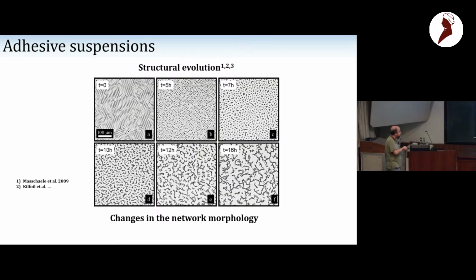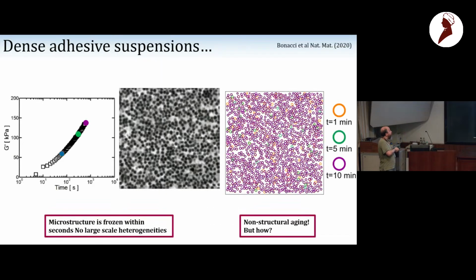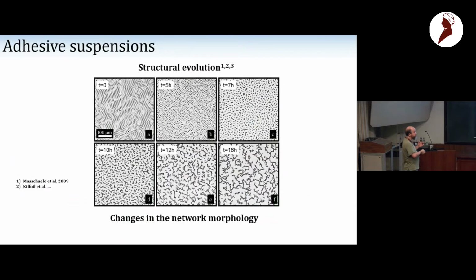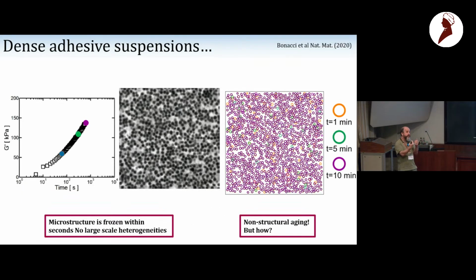Even in adhesive suspensions, people expect structural evolution. So in our case, we have adhesive suspensions where there is a form of gelation dynamics, but the gelation dynamics occurs in a dense system. Here you have gelation in a dilute system. When you have gelation in a dense system, you don't see so much motion because each particle is close to another one. So you can gel by a very rapid formation of a dense network, and you can freeze the microstructure within seconds, and then structurally nothing else happens.